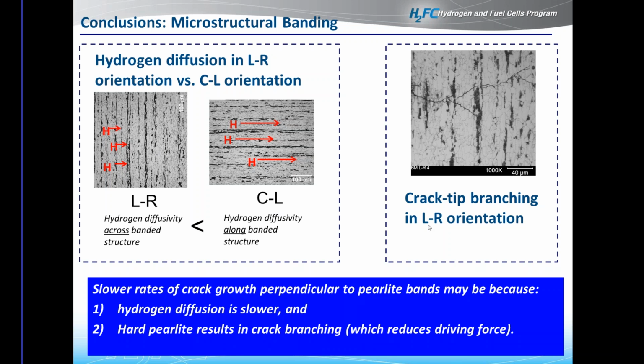On the right, we see the presence of cracks propagating through a banded ferrite pearlite microstructure, and in the LR orientation, what we actually observed was crack branching occurring. As the crack approaches these harder regions of pearlite, it actually branches, and in effect, what that does is shield the crack tip from seeing the entire driving force, or the whole stress that is applied, therefore reducing the driving force. So these two factors basically reduce hydrogen diffusion, which ultimately results in a lower, or we'll say delayed, hydrogen supply, and the presence of crack branching shows that the microstructure does have an influence.